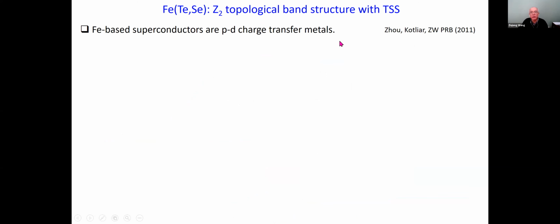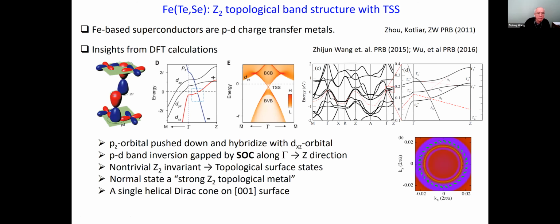And I want to emphasize the reason for this to happen. One can ask, why does it happen in iron-based superconductors? There are various reasons, but one of the most basic reasons, I think, is that iron-based superconductors are pd charge transfer metals as opposed to cuprates, which are pd charge transfer insulators. So the p bands are close to the Fermi level. And in FeTeSe, the tellurium atoms are big. So they hybridize, the pz orbitals between different surfaces really strongly hybridize. This pushes the pz orbital further down towards the Fermi level, and therefore it crosses the d bands, and of course crosses the Fermi level.